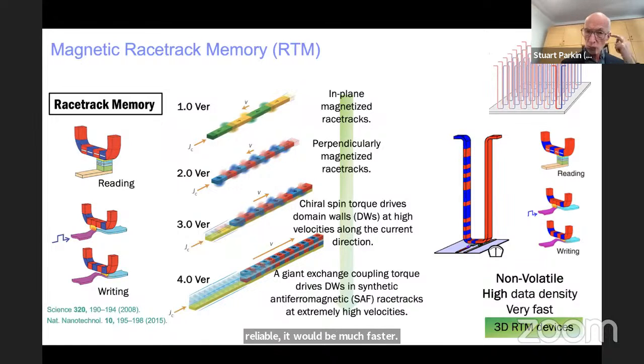And over the last 20 years, we've evolved the racetrack materials from initially in-plane magnetized racetracks formed from nickel iron alloys, which are known to have very, very large spin polarization of the current through spin-dependent scattering. When you pass current into that material, then the current itself could, through that spin polarization, carry spin angular momentum and cause the domain walls to move. And that's what we demonstrated in this paper in Science in 2008, in which we could, with current pulses, move a series of domain walls backwards and forwards within a racetrack formed from a nickel iron cobalt alloy.